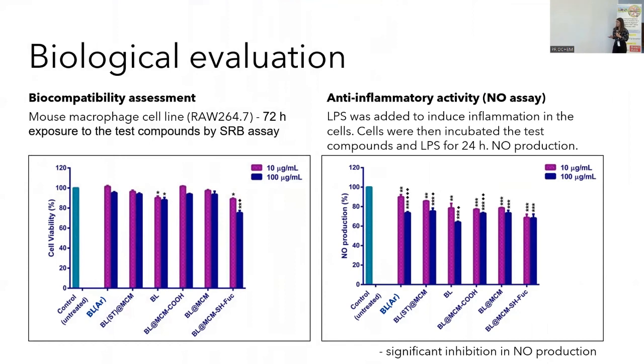The biological evaluation was assessed using mouse macrophage cell line RAW264.7. The biocompatibility was assessed, and the other analyses were assessed using two concentrations, 10 micrograms per milliliter and 100 micrograms per milliliter. For the biocompatibility assessment, all the samples possess almost no cytotoxicity, but one, the fucoidan-coated nanoparticles, showed a slight decrease in cell viability, but it can be considered safe.